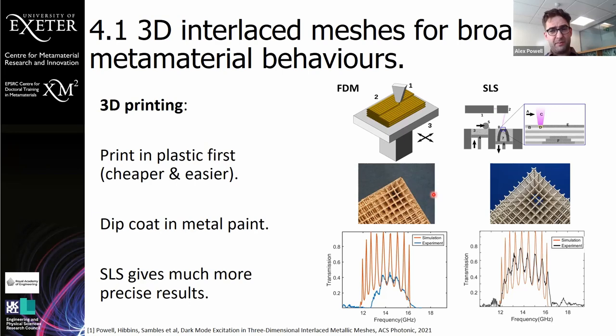And we didn't fancy trying that with a double mesh. So we then looked at SLS, this powder sintering method, but this time we used polymers and then dip coated it in conductive paint afterwards.